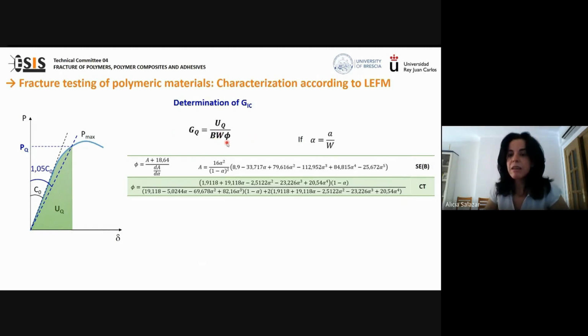Phi is a calibration factor shown in this table for the 3-point bend and the compact tension specimens. The following cross check must be performed. The value of the Young's modulus E over 1 minus the square of Poisson's ratio should be larger than the square of K1C over GQ. The maximum difference should be 15%.